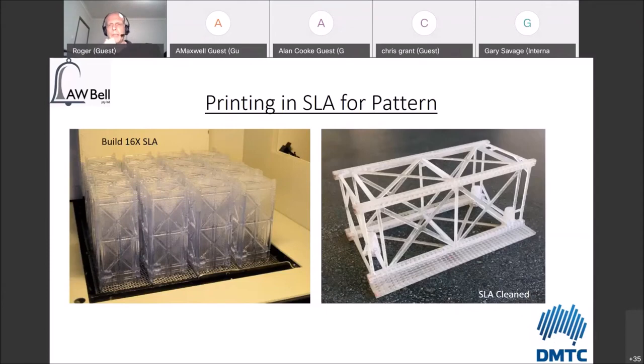On the right-hand side, you can see one of the SLAs which is cleaned up, and I still have some of these. I have one here, but you can get a feel for the size of it. They're not big. This particular one's around about 10 centimeters on the end and around about 20 centimeters long. It's got some flat sections on it that you see here, which were meant for mounting onto a flat panel, but you can see the general geometry of it's pretty complex. It's just very, very open, and so that's what we were looking at casting.